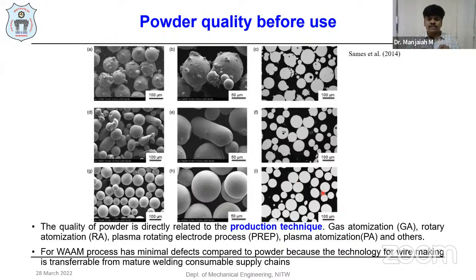The quality of the powder is directly related to the production technique, meaning how it is manufactured. The powders are produced with atomization processes, whether gas atomization, rotary atomization, plasma rotating electrode atomization, plasma atomization, or other kinds of powder production processes. For WAAM, the system is already well developed, because we are using welding wires, either TIG wires or MIG wires. Because of that, we have very minimal defects compared with powder bed manufacturing technologies. Because wire making is already standardized, you can transfer from the already matured welding consumable supply chains.